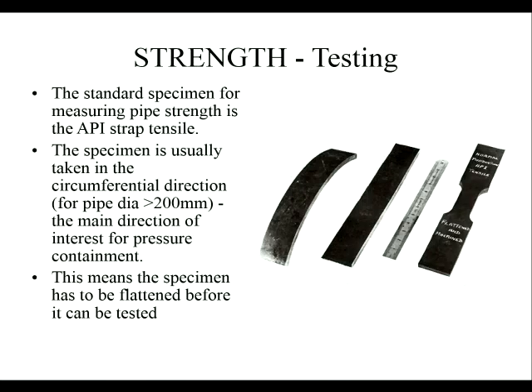So how do we do that? Well, the standard test method for a piece of pipe is called the API strap tensile test. So you cut a section of pipe out, and you can see it's cut in the hoop direction around the pipe. And then you put it in a press and flatten it. And then you cut some restrictions on each side to form what we call the gauge length. So we machine it to the shape of a tensile strength test, and then we put it.